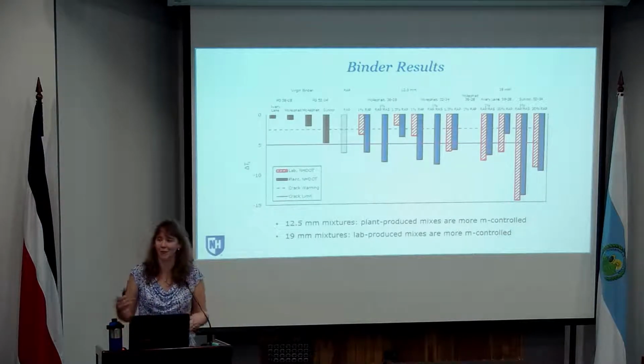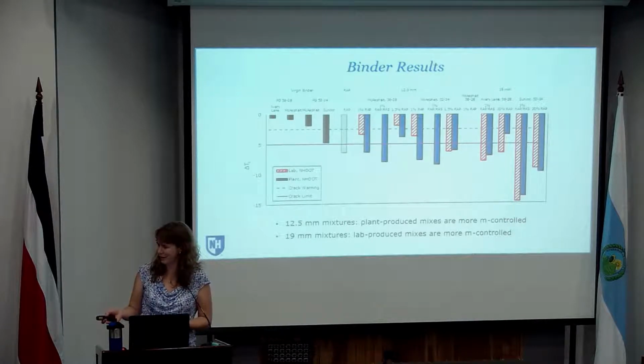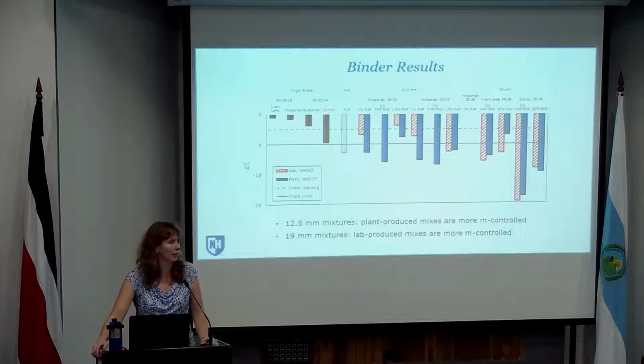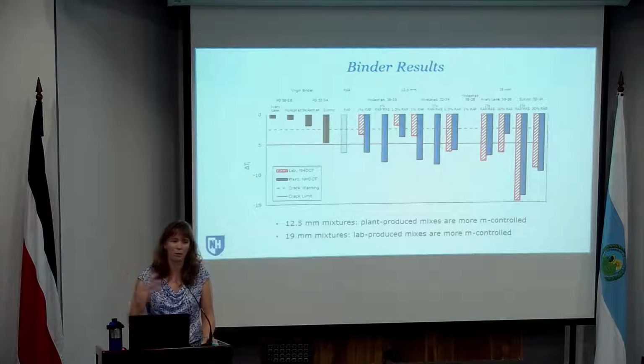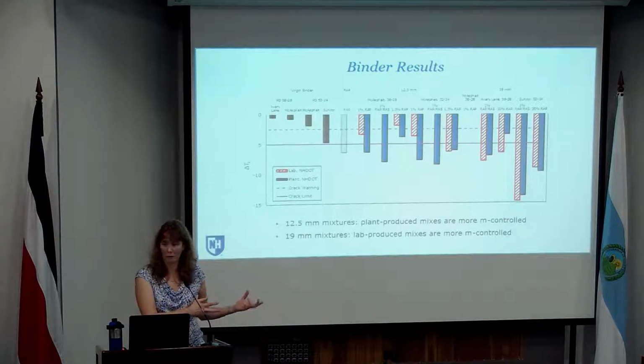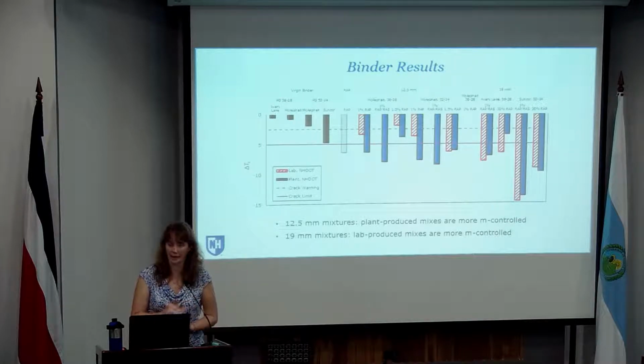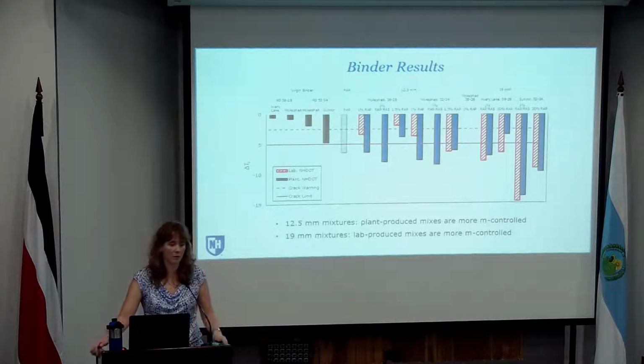So REOB is, I don't know, do you guys deal with REOB? Not so much. Okay, so just a quick explanation. REOB is recycled engine oil bottom. So essentially when motor oil is recycled, okay, and that's refined and used, the residual that's left over at the end can be used or has been used relatively frequently, depending on the area of the country, as an additive to asphalt binders, specifically some of the softer binders, to get them to meet the PG grade.